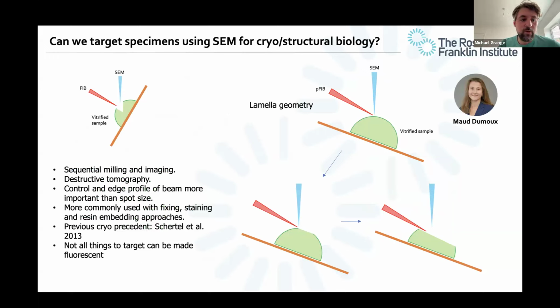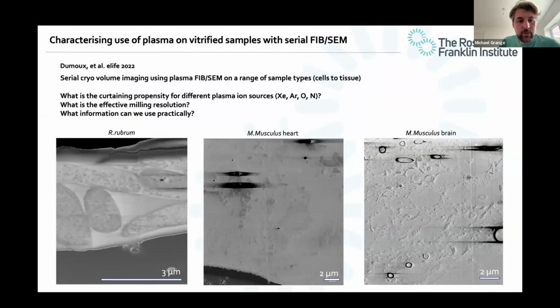So as you mill, you can image, and you can image after milling several times in a sort of iterative fashion in a so-called destructive tomography. Part of this is important because what we want to know is which ion behaves better than the other. So if we have access to argon, xenon, nitrogen, oxygen, we started doing some serial FIB-SEM experiments, which you can see here.